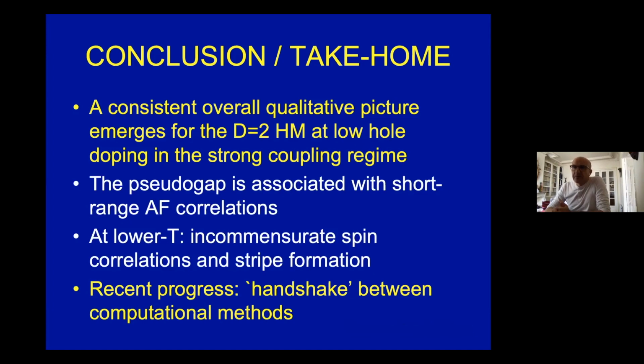I hope to have convinced you in this talk that a consistent overall qualitative picture, and sometimes quantitative agreement between different methods, emerges for the two-dimensional Hubbard model at low hole doping in the strong coupling regime. In this regime, the Hubbard model displays a pseudogap whose origin is now, I think, well established to be associated with short-range antiferromagnetic correlations, but at lower temperature, incommensurate spin correlations and stripe formation do develop, and that a very interesting and exciting set of developments realize some sort of handshake between computational methods, allowing us to establish this overall qualitative picture.